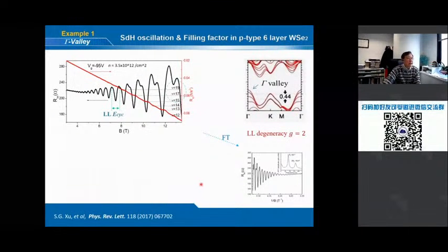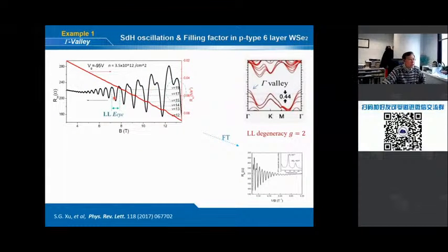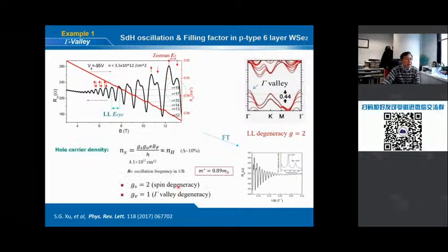And I show the first example. So you measure the oscillations. Basically, each peak represents each Landau level. You can identify the filling factors. And once the magnetic field is large enough, you see spin up, spin down, spin up, spin down. And that represents the Zeeman energy. And we can determine other parameters like effective mass, degeneracy, and so on. So they have to do the analysis.